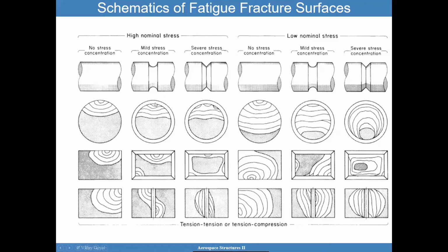And again, this gap represents that stress concentration. So here's an area that we're looking at, which is right in the center, right there. If I look at a severe stress concentration, you're going to have multiple initiation points, and the beach marks will be less. You're going to have fewer beach marks, and you're going to have a ductile failure or brittle failure. That's for a circular sample.